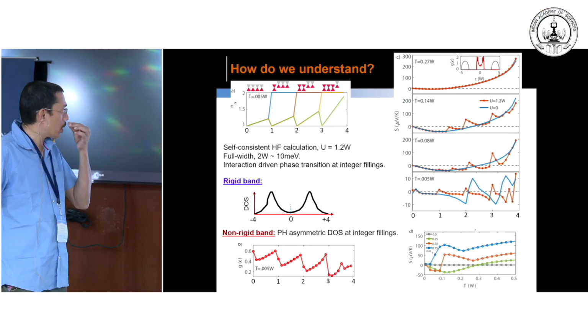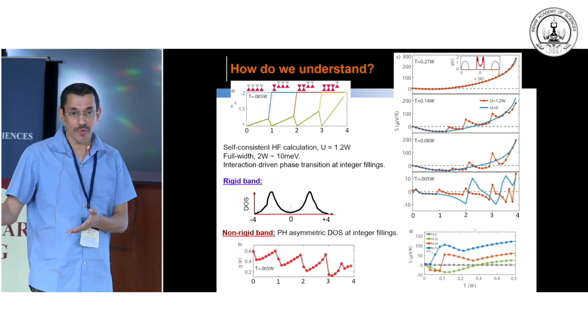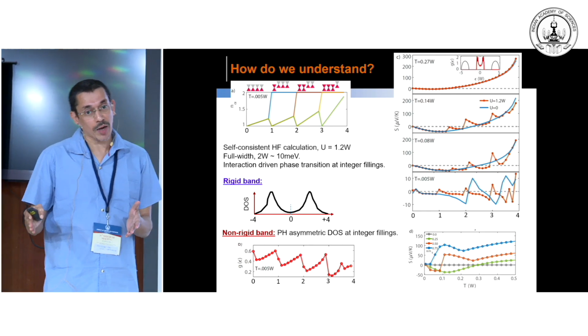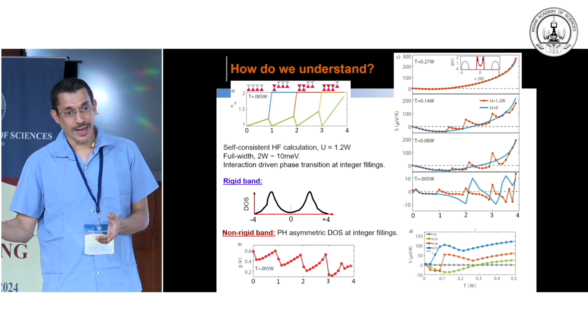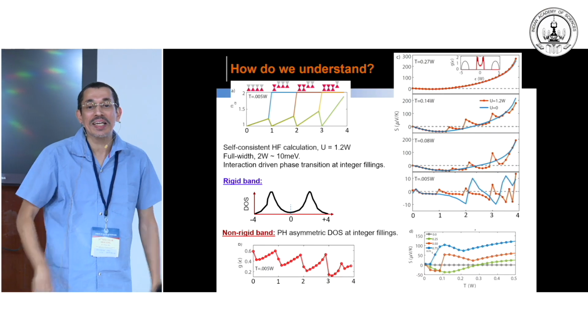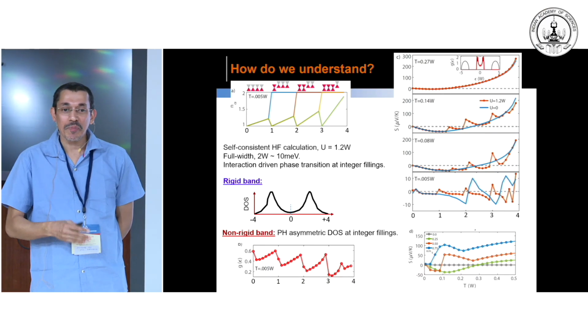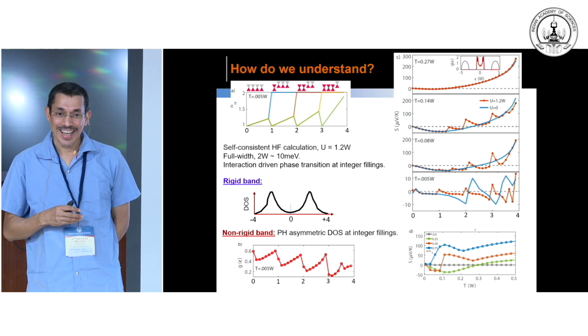Well, that is not true, because at the same density, if you look at graphene for example, thermopower is extremely low. Yes. Right. But then you don't have the flat band. Flat band gives you the large effective mass. See, if you look at the phenomenological expression for Seebeck coefficient, it's directly proportional to effective mass. But you cannot use it, because the Mott formula is not valid here. No, because in this system, the Mott formula you cannot utilize. That's not the Mott. This is based on Mahan's work, G.D. Mahan's.